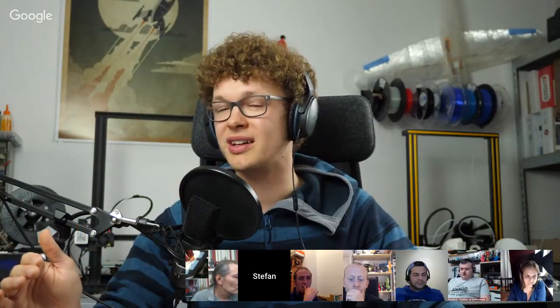Yeah. Oddly, I've never heard of somebody actually using, or nobody's ever talked about using a dehumidifier in the room that they're printing in. Well, if you're in the UK. Well, the dehumidifiers usually dehumidify up to like 40% relative humidity, and that is still too much for storing filaments. The dry boxes that I have have a hygrometer in there, and the humidity is always below 10% relative humidity. And I think that is fine. I don't know where it's starting to pick up moisture, but at some point it does. And with a normal dehumidifier, I think you don't get down as much.